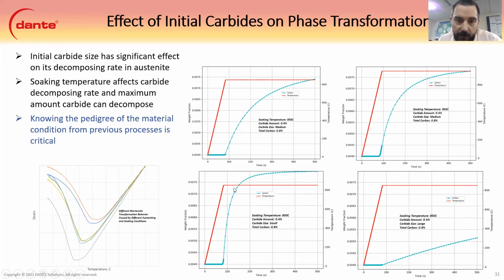Obviously, you can see that the small carbides dissolve really quickly into the matrix. You're leveling out at about 300 seconds, whereas with a large carbide, you don't even get close to the carbon level of dissolving them all. So knowing your carbide size and knowing that prior is really useful. That ultimately has an effect on martensite transformation behavior. And you can see that in the image at the bottom left, the different martensite transformation caused by the different soak conditions. So more carbon will decrease the temperature at which martensite starts.